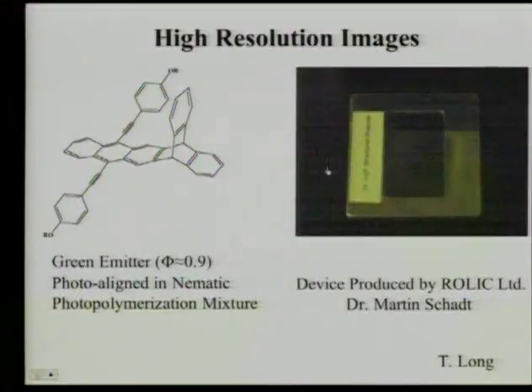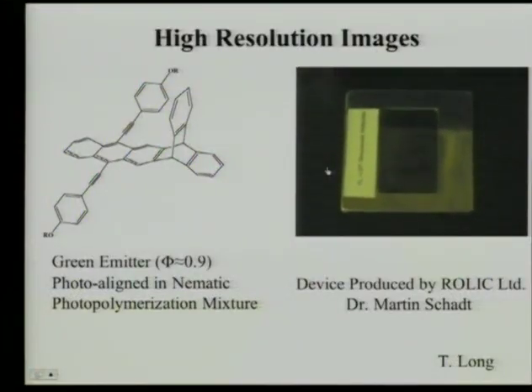So you can do things where you take these molecules, and this is something we did in collaboration with a company in Switzerland called Rolic, and they use a photo alignment to write images into materials. We put a fluorescent green dye in this, and what they've done is use an optical orientation in the liquid crystal simultaneously with polymerizing it. They've been able to write this image. Now, this image is not that fine because the liquid crystal is being polymerized. It has a very weak field aligning it, just an optical field, and you don't get a high resolution image out of that. But you get a high resolution just essentially in a refractive index sense.